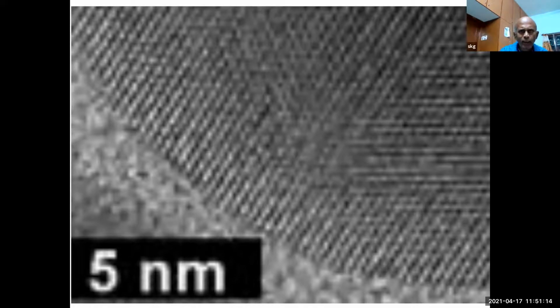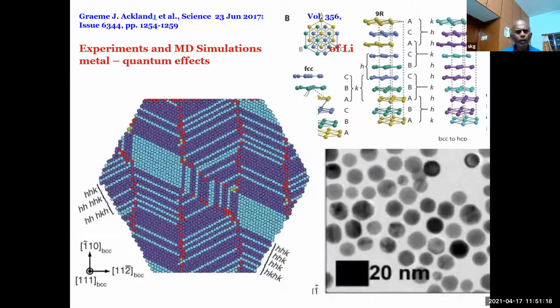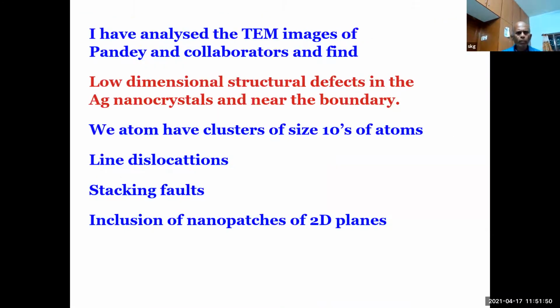So now I estimated the number of things available. Unfortunately for me, there was a nice theoretical work in the context of lithium available by some group. So they had studied experiments on MD simulation of nanoparticles. What you find is, because of kinetic barriers and so on, you never get a perfect single crystal. You have lots of stacking faults and lots of clusters and so on. So I found that similar things happen in Thapa and Pandey. So this is what I find by my analysis: line dislocations, stacking faults, inclusion of nanopatches of 2D planes in Thapa and Pandey's sample.